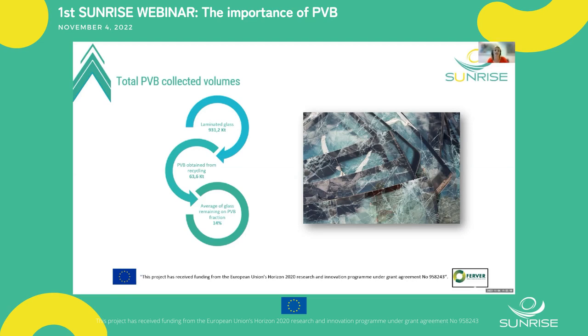And within this laminated glass, we asked how much PVB is obtained from the recycling of laminated glass, and we reached a little bit more than 63,000 tons, which corresponds to 6.8% of the total laminated glass that is collected and treated. We also added another question, an estimation of the percentage of glass pieces remaining stuck to the PVB waste, which is around 14%. This 14% should reduce the volume of PVB obtained in the previous question.